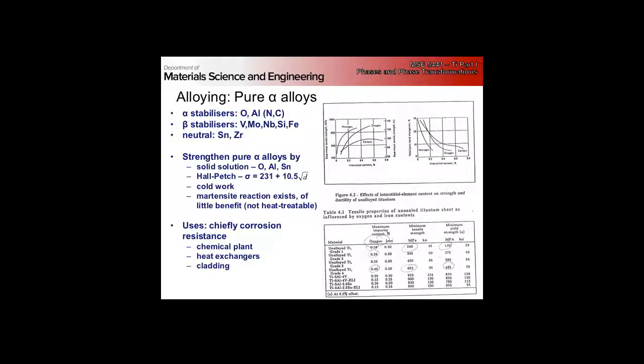The important stuff that I really want everyone to recall right away is alloying — common alloying elements. The alpha stabilizers are oxygen, aluminum, nitrogen, and carbon. Oxygen, nitrogen, and carbon are interstitial. Aluminum is going to be substitutional.